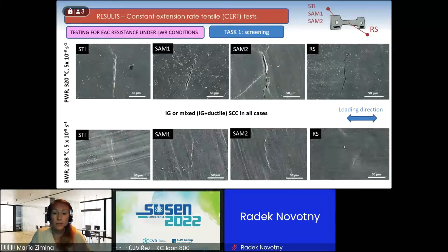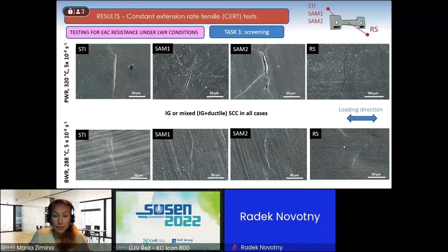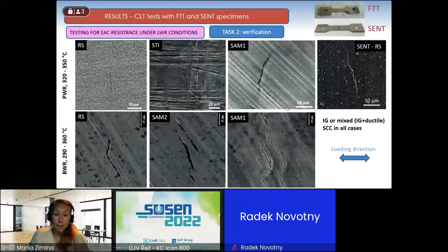After the first task, after the screening, using this accelerated testing, we observed intergranular or mixed cracking in all cases, in both two environments, and for all four surface treatments. In case of task 2, initiation testing, we observed the same situation with a bit different structure of the cracks, but still intergranular or mixed. And as Radek mentioned today, we can't really talk about the mechanism of this cracking using this accelerated testing without performing the crack growth tests.